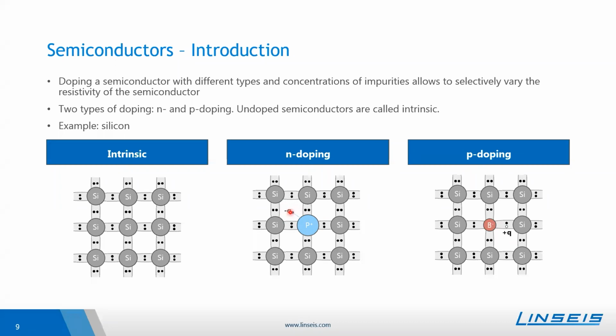The p-doping describes the other side, so that one uses an atom with a lower valence. In the case of silicon, this can be boron, for example. And with the boron, there will be an additional hole inside the lattice. This is displayed here with the white part.